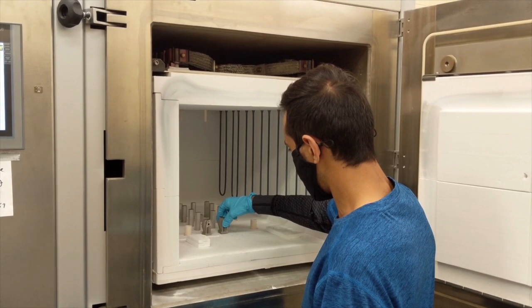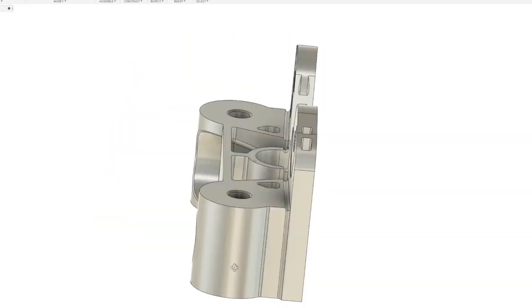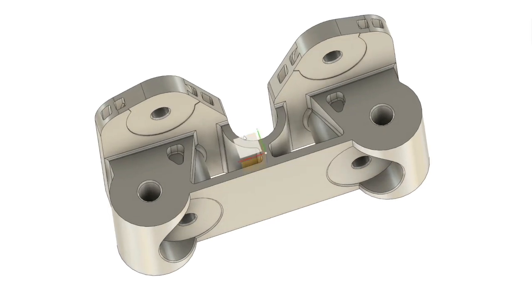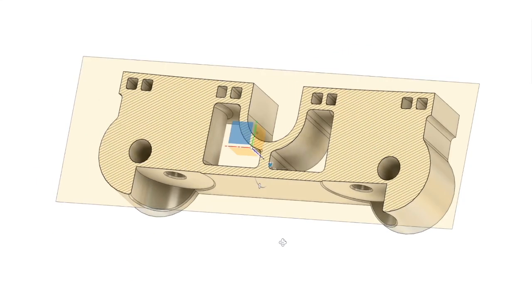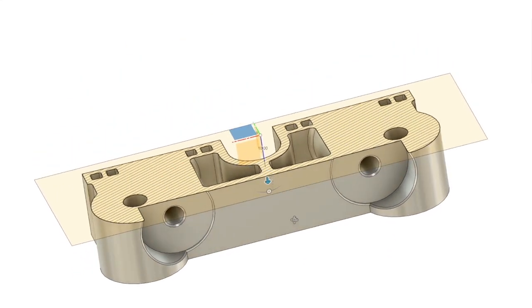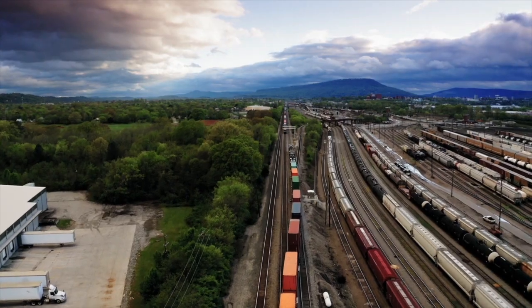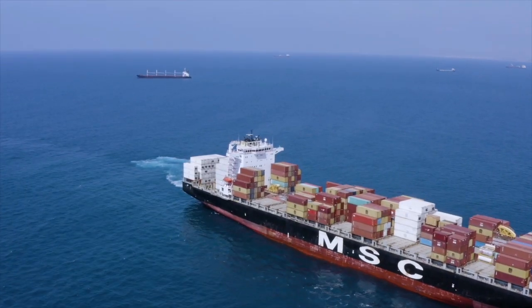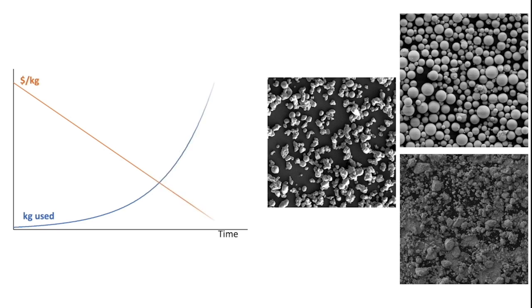Secondly, a high-strength alloy with simple post-processing will enable more optimized future designs without the complications of solution annealing and quenching that can result in residual stresses and distortion. Finally, a high-strength alloy with broad industrial use and multiple powder suppliers will ensure both availability of powder and a competitive pricing environment, especially as demand grows and additional sources of alloying elements become available.